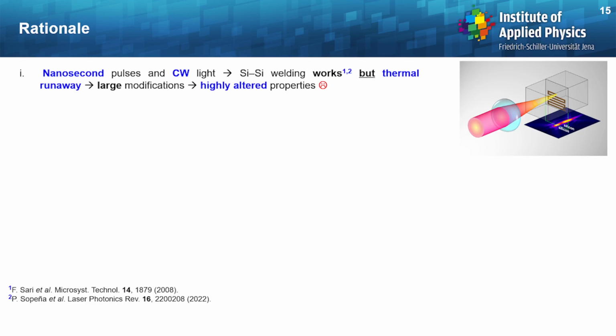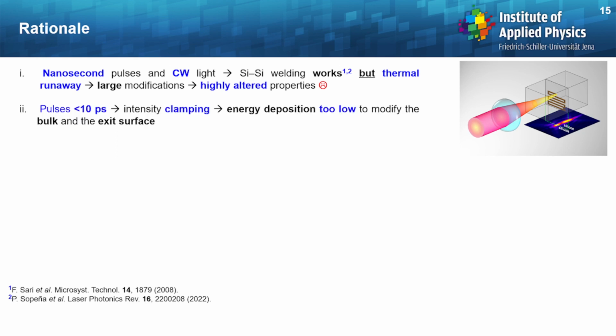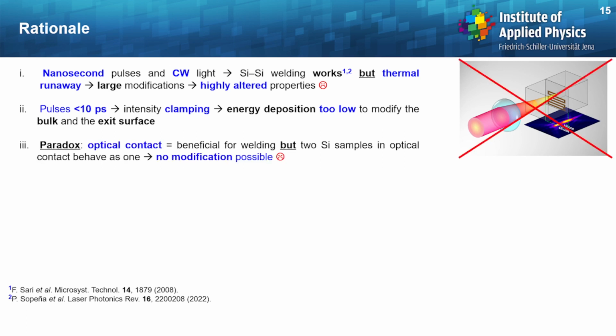From the literature, we know that it is possible with nanosecond pulses as well as continuous wave lasers to bond silicon to silicon, but unfortunately, the thermal runaway during the interaction leads to large modifications, which means that the samples may be heavily altered in terms of optical and electrical properties. On the other hand, when you have pulses that are too short, then you get this intensity clamping phenomenon, and the energy deposition will be too low to modify both the bulk and the exit surface of the material. And here comes an interesting paradox, because usually optical contact is preferable when you want to weld two samples together.